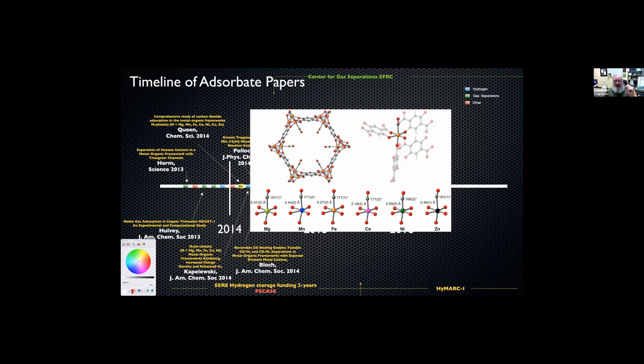And Matt Hudson did this work with Eric Bloch, where there's a high spin state for each of these metals if they're in the transition metal state. And so you can get reversible adsorption and desorption of the carbon monoxide complex, which is normally not what happens. Usually it induces the low spin transition and there's a really strong binding and backbonding from the transition metal to the carbonyl complex, and that becomes irreversible. So these metal organic frameworks showed some really unique properties. And again, some of these systems had never been measured. The CO2 interaction with some of these metals had never been observed before.